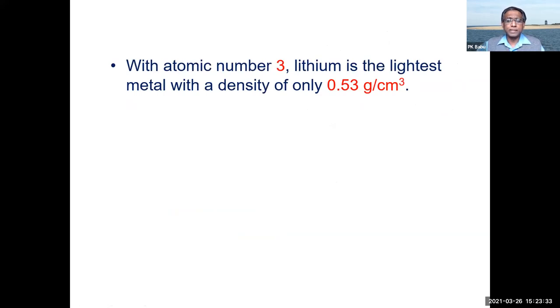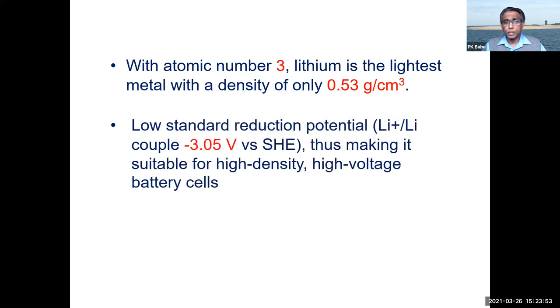So with atomic number 3, lithium is the lightest metal with a density of only 0.53 grams per cubic centimeter. See the importance of that. You can pack a lot of lithium atoms in unit volume, just half of the density of water. The low standard reduction potential, remember the active series table which I showed you, lithium has the lowest in that series, negative 3.05 volt versus a standard hydrogen electrode, thus making it suitable for high density, high voltage battery cells.